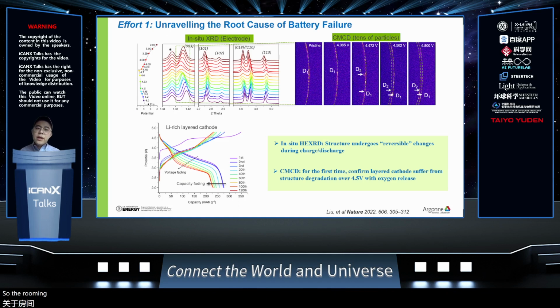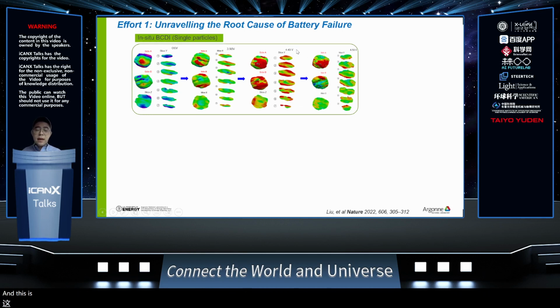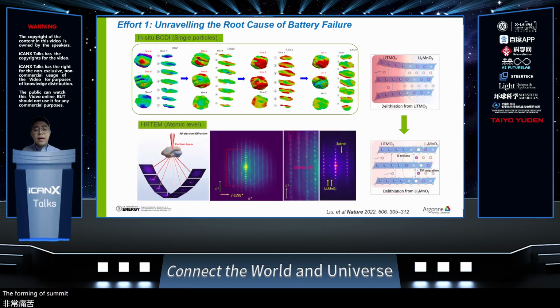So the remaining question is, what drives this structure degradation? We went further down to the single particle level using in-situ BCDI, and we were surprised to find the lithium-rich cathode suffers from severe lattice strain in every single cycle. Also, this lattice strain accumulation reaches the maximum at 4.43 volts, and this is destructive enough to trigger the structure degradation. The following atomic level high-resolution TEM confirmed the lattice strain occurs at 4.5 volts, together with the new spinel phase generation.